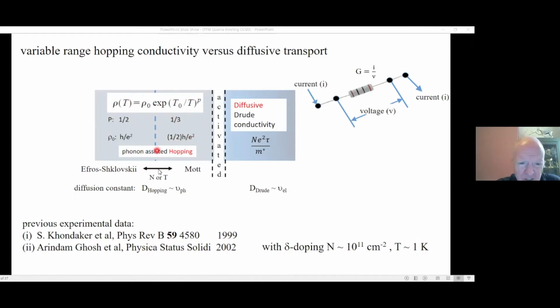At lower temperatures, we shift over to a different type of variable range hopping called Efros-Shklovskii hopping. The power changes, P is a half, and the prefactor ρ0 changes. Interestingly enough, in terms of diffusion, when you're in the Drude region, we've got a diffusion constant that's something like an electron frequency, and when we're in the hopping regime, we've got something like a phonon frequency, and they can be 3 orders of magnitude different.